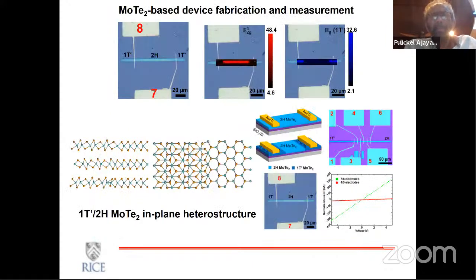And one thing we were trying to do was to make this 2H structure as a channel for a device, and the 1T prime, which is more metallic, as a contact layer. And we were able to do that. You grow these structures, go around and search for these different phases, and then put your contact on the 1T prime area, and you get pretty good devices if you do that.